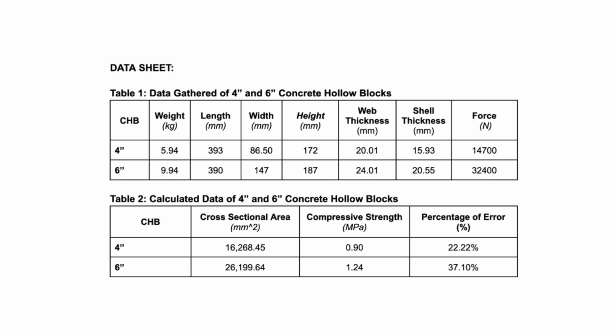Failing to meet the ASTM standard for physical requirements such as dimensions can compromise the strength or durability of a structure. Moreover, Table 2 demonstrates that the 6 inches CHB had a compressive strength of 1.24 MPa, which was higher than the 0.90 MPa of the 4 inches CHB.